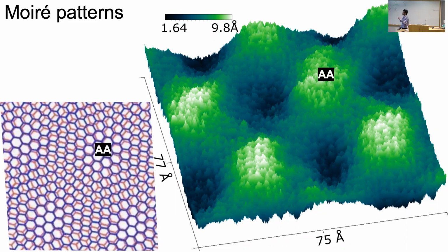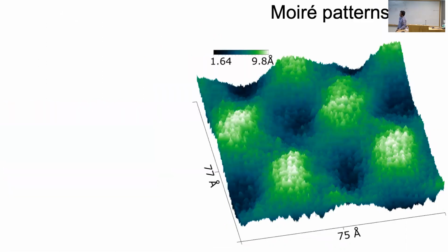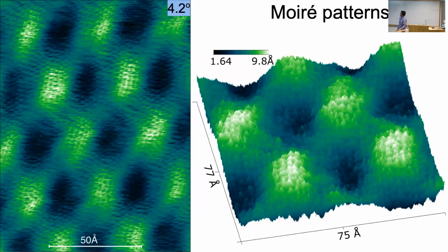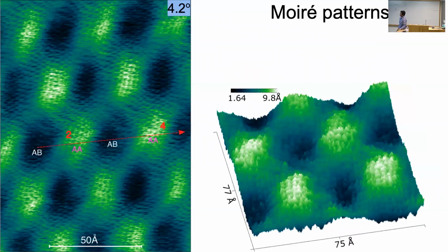They have weak interlayer coupling, so they are pulled out of plane. Whereas the valley regions, which are the dark regions, are called AB domains, where there is strong interlayer coupling. That's a 2-dimensional image of the same 3D picture. And you can see that these are the hilly regions and the dark regions are the AB domains.